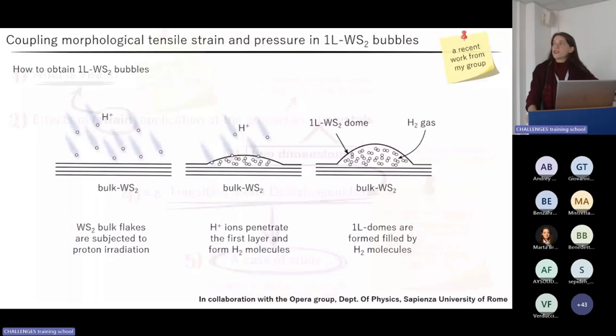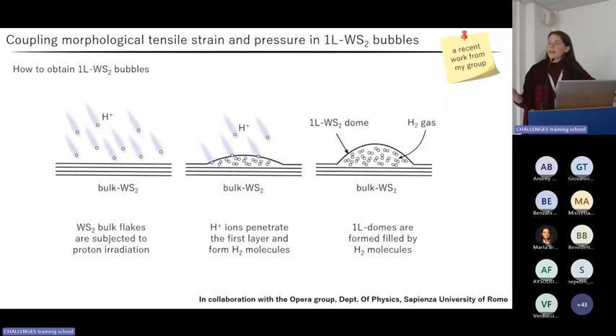The system under consideration is a monolayer bubble of tungsten disulfide. These bubbles are obtained by irradiating a bulk flake with protons. After impinging on the bulk surface, protons penetrate the first external layer, and then they recombine, forming hydrogen molecules, which remain trapped in the interlayer space, forming these monolayer domes filled with gaseous hydrogen.